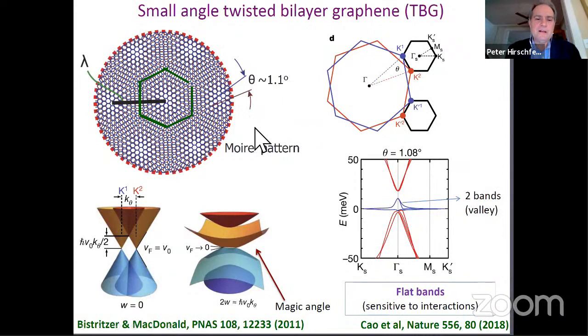In particular, it was shown already before the experiment by Alan MacDonald and this person whose name I don't know, Bistritzer, that if you rotate to this magic angle, what happens is the band structure of the material, no interactions yet, just ordinary band theory, goes from being a Dirac cone that we know about, the double Dirac cone from the graphene system, to a flat band with very narrow, very narrow bands, a series of very narrow bands near the Fermi level. And you can see this picture here for 1.08 degrees that these bands might be present there.